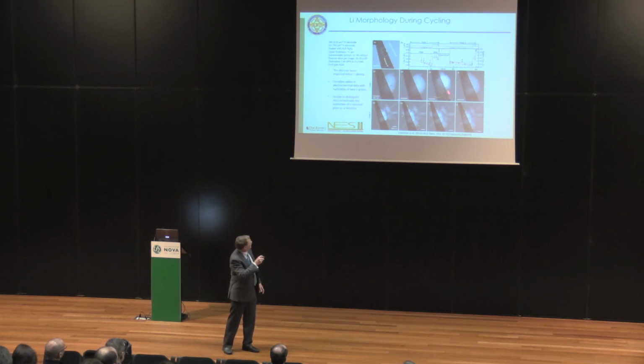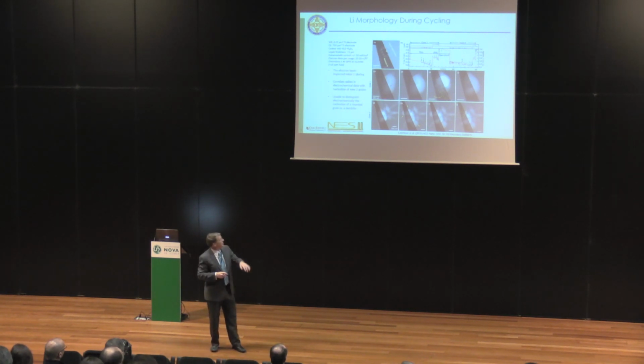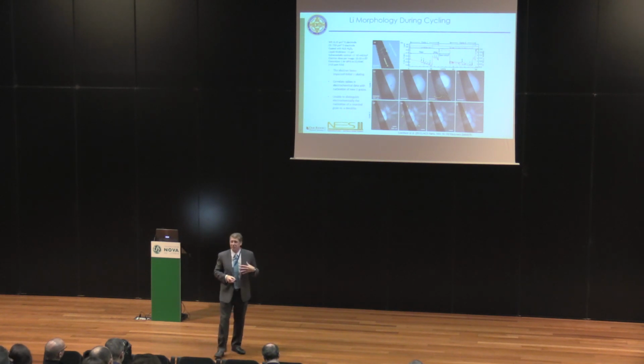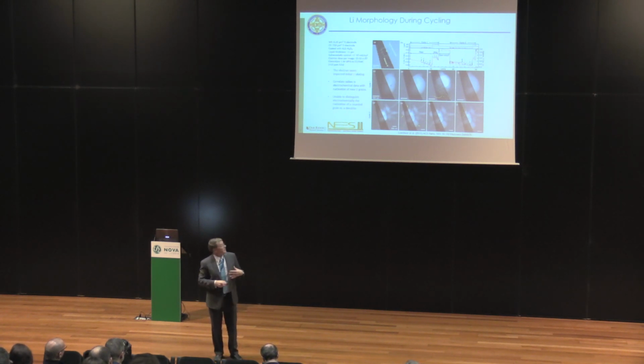It's a little bit hard to see, but outlining these yellow lines is a dendrite that was growing underneath, or above, this contact, so it was coming out from underneath. All right, they then run a stripping cycle where they pulled off all the lithium that they could, then let it sit for a little bit, and then they plated once again.